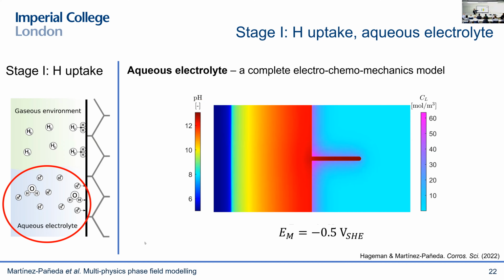And these are some kind of representative results. So this is for a given choice of applied potential. And you can see in the electrolyte a pH distribution. You can see that it changes quite drastically from the bulk to the inside of the crack. And then here you see the uptake of hydrogen concentration.